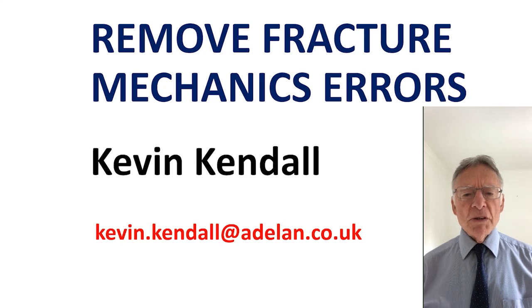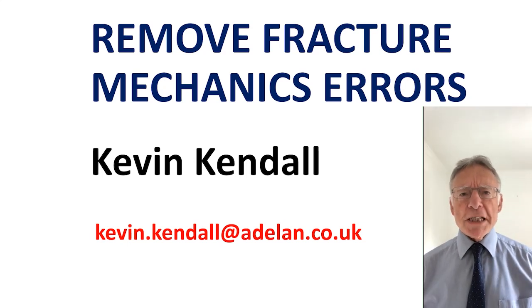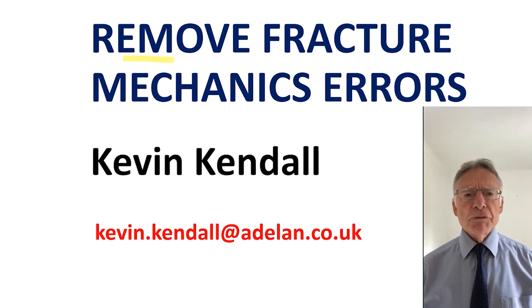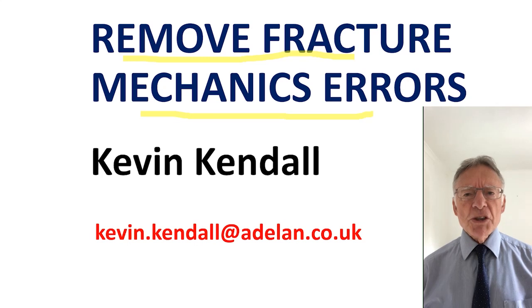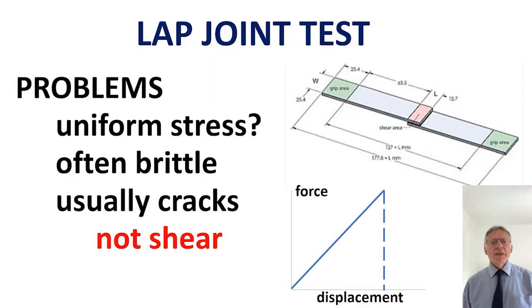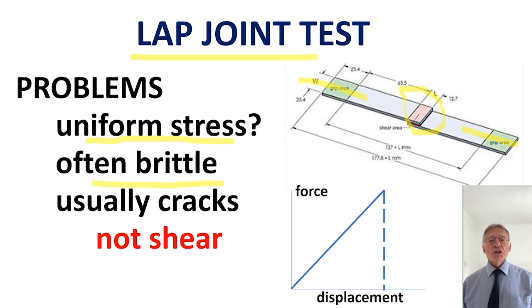That was a great presentation on new experiments cracking welded composite sheets. Now I want to try to remove errors from fracture mechanics for this test. We must use the Griffith energy argument and apply his conservation theory. It's a simple test. You take the two sheets, overlap them and weld the surfaces together, and then you apply the tensile forces here and here. The problem is that the stress is not usually uniform across the joint. Also, the joint is brittle and cracks. A typical force displacement curve can look like this. It's elastic and then goes bang. It's not shear, it's cracking.